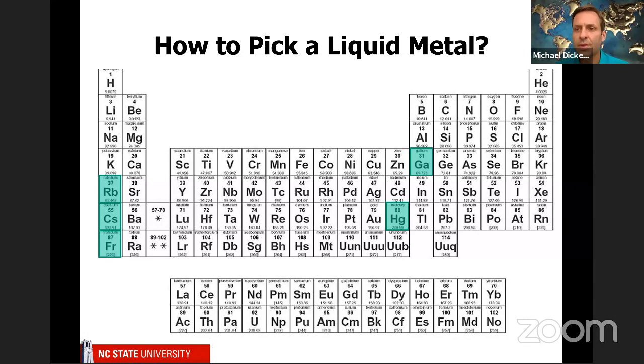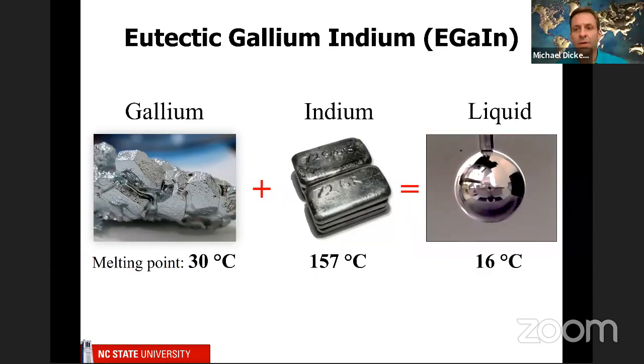And you'll notice that's sort of important, and I'll drive home this point in a second, that it's right below aluminum on the periodic table. So that kind of makes them brothers or sisters in the sense that they're going to have similar properties. But there's one major difference, and that is that gallium has a low melting point. So this is a crystal of gallium, and it melts at 30 degrees Celsius. For my American friends, that's about 85 or 86 Fahrenheit. So if you held it in your hand, it would be enough to melt it.